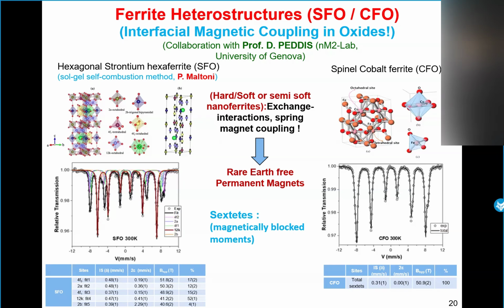In the hexagonal structure of strontium hexaferrite, we have 5 sites of iron, inequivalent sites of iron, distributed in 3 octahedral sites, 1 tetrahedral site and 1 trigonal bipyramidal site. So the configuration of these spins is presented here. So this material is a hard material and is characterized by a strong magnetic anisotropy.